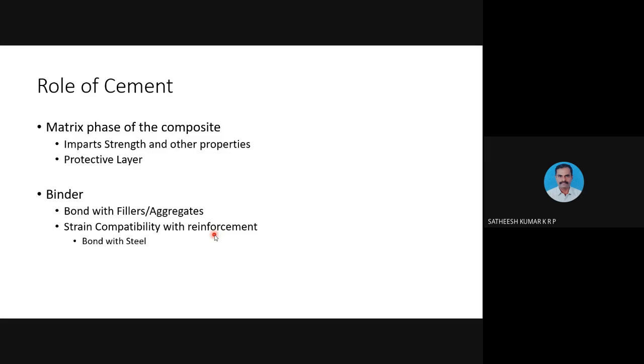So we need some form of bond between this reinforcement and the concrete. That is provided by the cement or the binder in our case. But apart from this, it also acts like a protective layer because this forms the matrix phase, which contributes a minimum of 15% to a maximum of 30% in the concrete. This covers all the materials. So this forms the protective layer for the concrete.